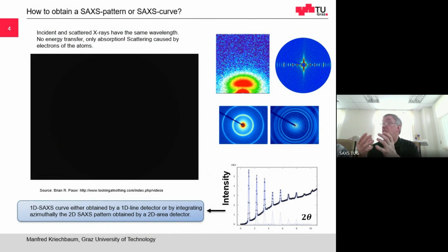But as long as you have inhomogeneities in your sample, so high and low electron density, this gives rise to a scattering pattern. The scattering pattern looks like here to the right. You can get the two-dimensional scattering pattern, which is either isotropic or anisotropic. If it is an isotropic scattering pattern, then you can make a radial integration and get a one-dimensional scattering pattern, which is intensity versus the scattering angle, displayed here. So you just integrate the spectra to get the one-dimensional scattering curve or diffraction pattern, intensity versus scattering angle.